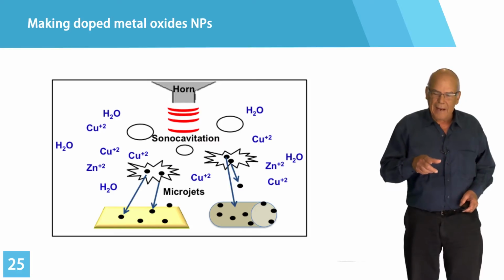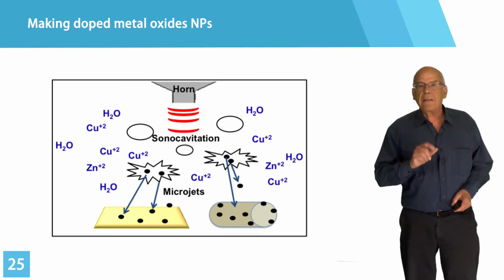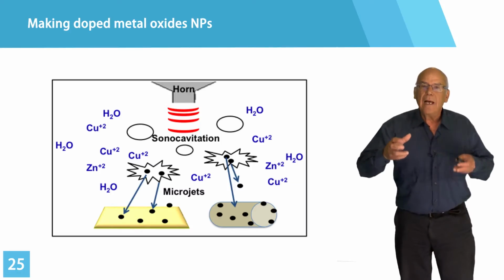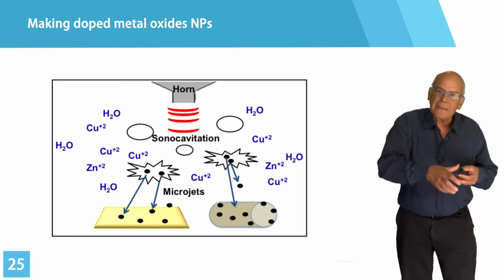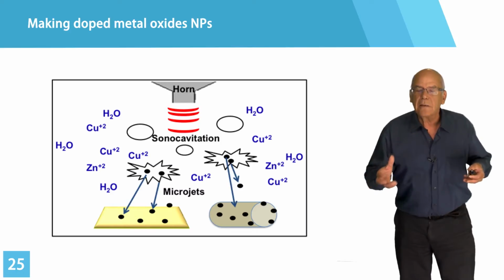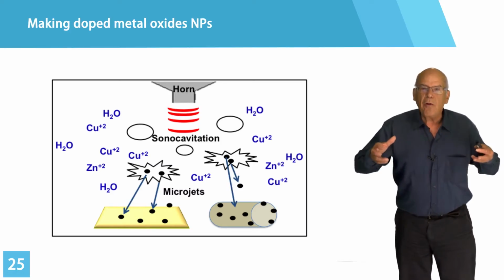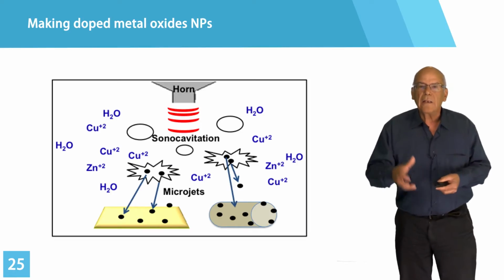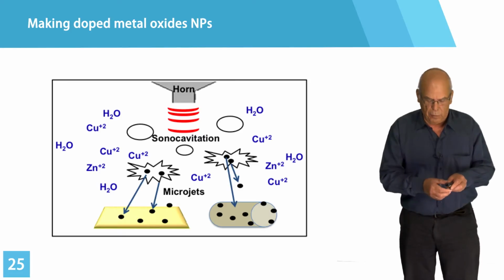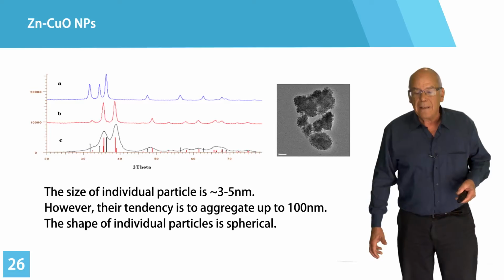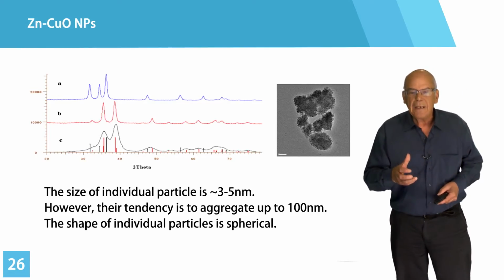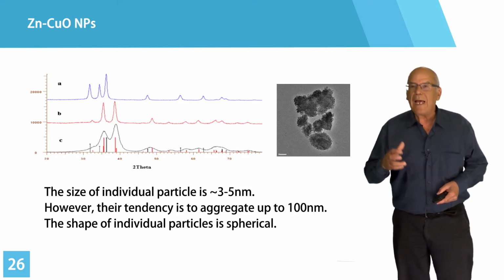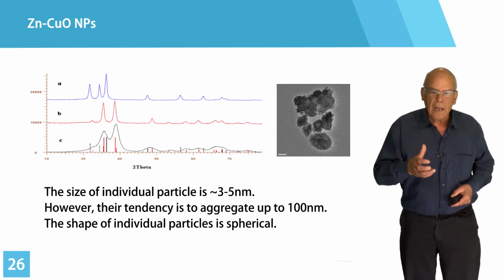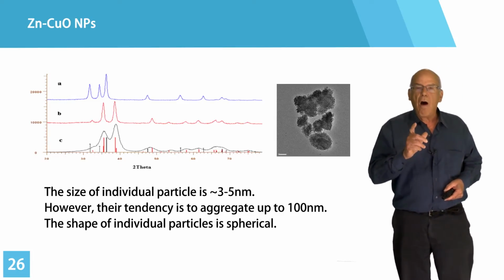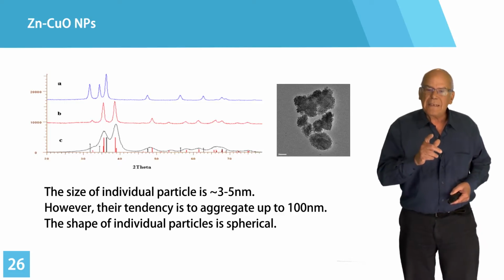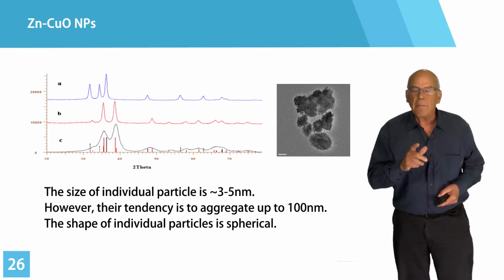Here we are showing the formation or fabrication of the mixed metal oxide. It requires that you add at one time a source of zinc ions and copper ions, and you do the hydrolysis that I showed you before, namely hydrolyzing simultaneously the two ions, forming this mixed oxide that I mentioned before. And how do we know that it's indeed mixed? This is dependent on shifts in the XRD, because here we are demonstrating the XRD of zinc oxide and copper oxide, and when you look at the position of the peaks, you will see that when we compare them to copper oxide, it's a little bit shifted.